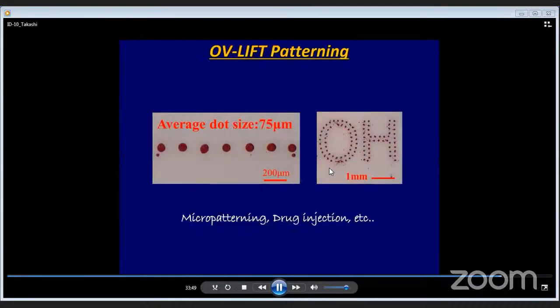In fact, at this moment, we can precisely pattern dots onto the receiver. In this case, the viscosity is about 10 pascal second, a very highly viscous material. The dot diameter is typically 50 micrometer, 75 micrometer, or something like that. Of course, we can shrink the pattern dot much more, to 30 micrometer, 40 micrometer, by just changing the numerical aperture of the objective lens. We can pattern such a beautiful character onto the receiver substrate. We also mention that this technology must be available for drug injection or further micro-patterning, for example, of electric devices.